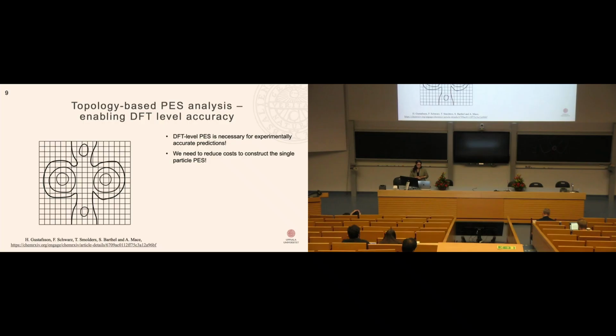Okay, so with this grid-based method, the computational cost is significantly reduced compared to molecular dynamics, but to be able to approach experimental accuracy, a DFT level of theory is necessary. And if we also want this approach to be practically feasible for studying large numbers of materials, we need to reduce the number of explicit energy calculations for constructing the initial single particle potential energy surface without losing accuracy. So what we basically do is construct our single particle potential on the DFT level of theory, and then the multi-particle correction is a classical Coulomb interaction.